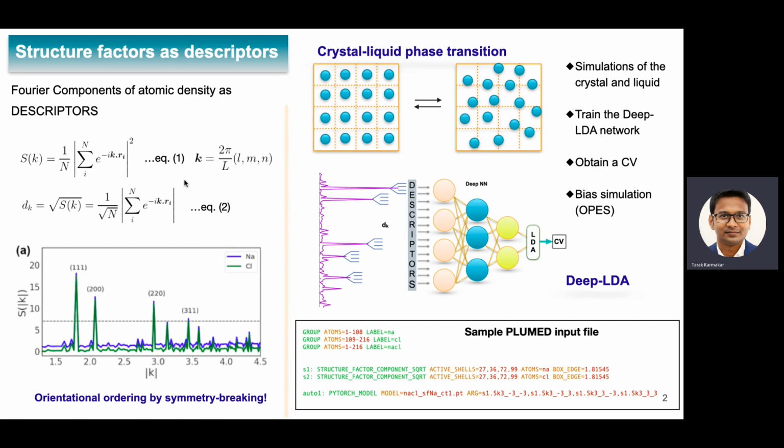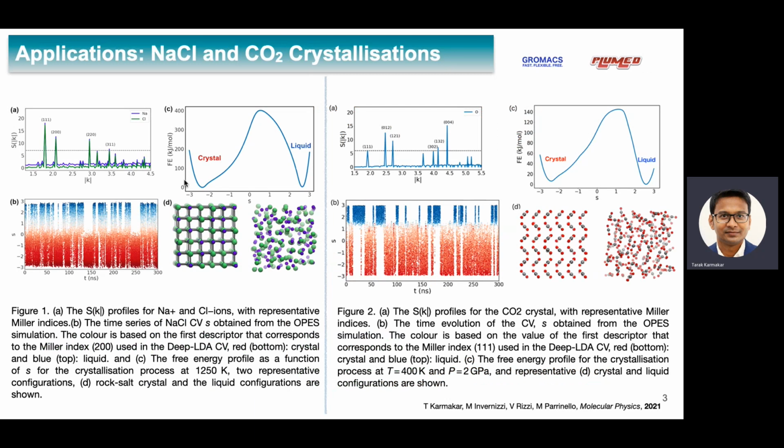We applied our approach to study the crystallization of two different systems. The first one was sodium chloride, and the second one was a simple molecular system, carbon dioxide. A large number of transitions from the crystal to the liquid phase or the other way around allows us to calculate the converged free energy profile.